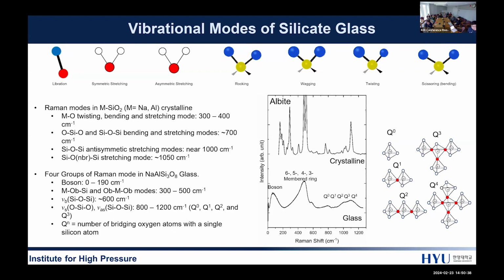The boson peak appears below 200 inverse centimeter, and metal oxide and silicon oxide modes are observed in the 300 to 500 inverse centimeter range. Silicate membered rings, like 6, 5, 4, and 3 membered rings, are observed below 600 inverse centimeter, and two specific modes are present from 800 to 1200 inverse centimeter. Q-species modes represent the number of bridging oxygen atoms, where Q0 means the individual silicate, and Q1, Q2, Q3, Q4 mean the oxygen connections: 1 oxygen, 2 oxygen, 3 oxygen, and 4 oxygens.